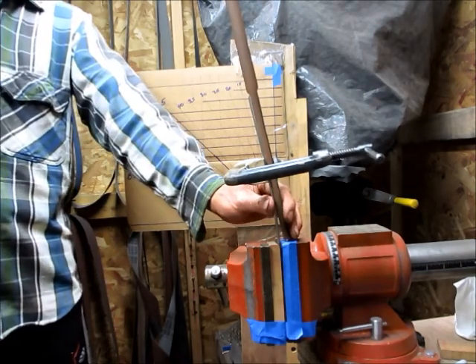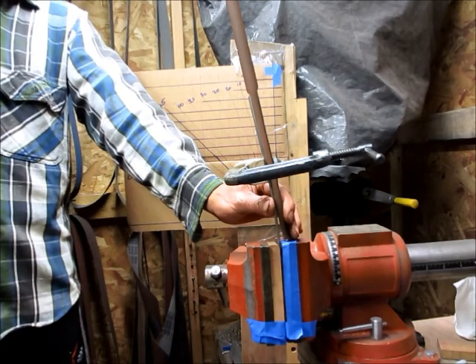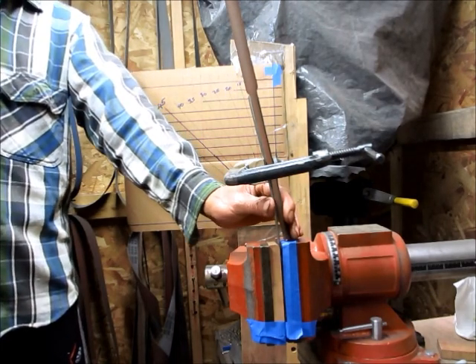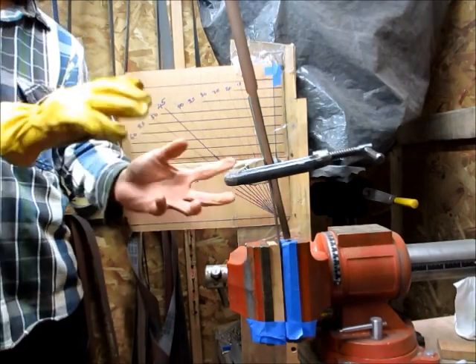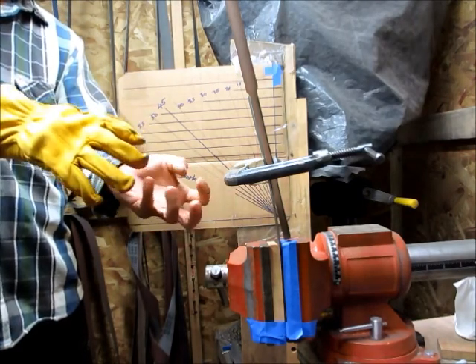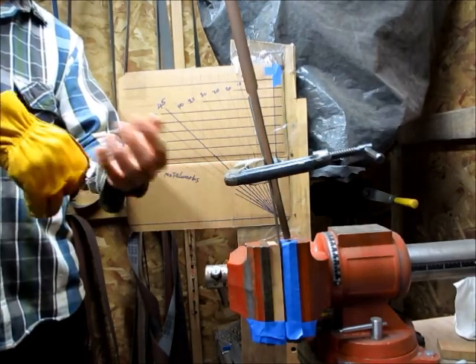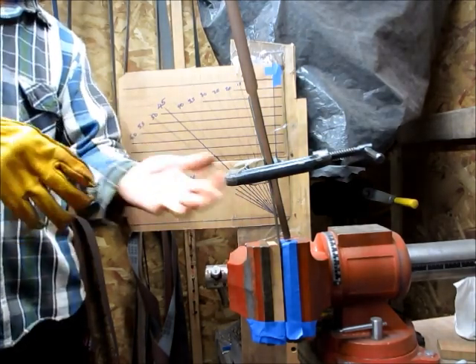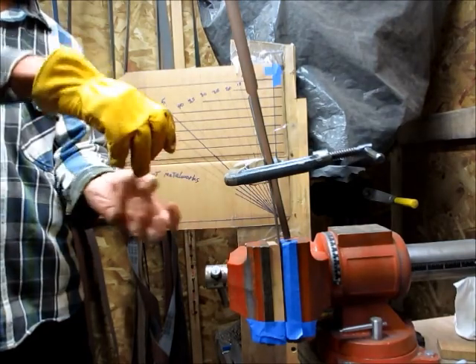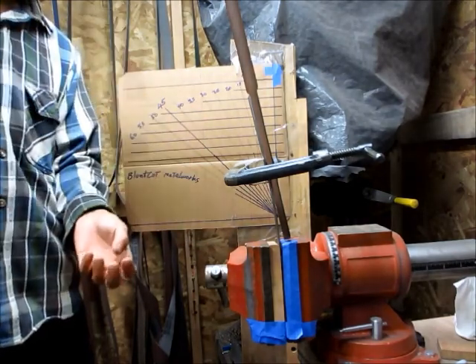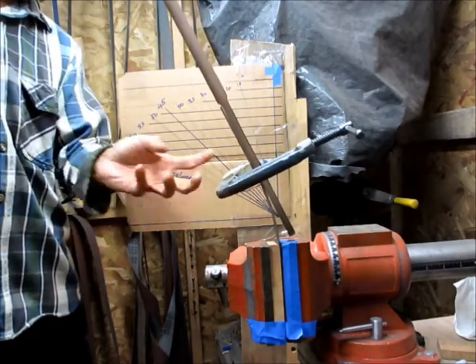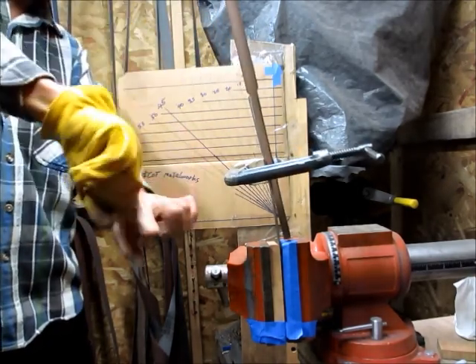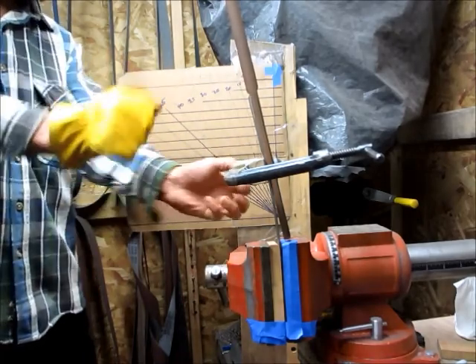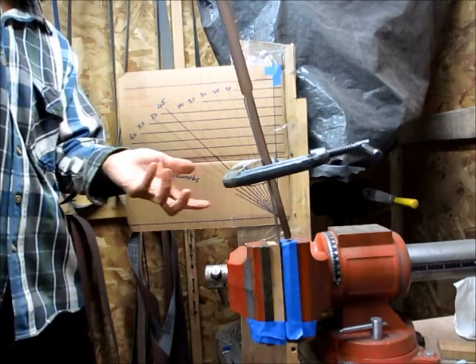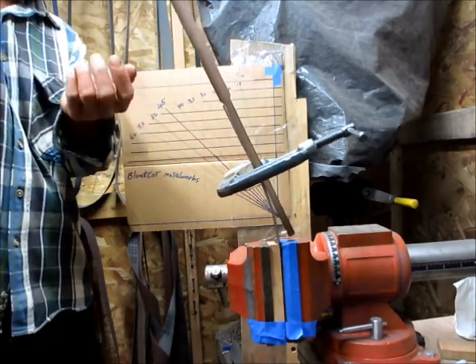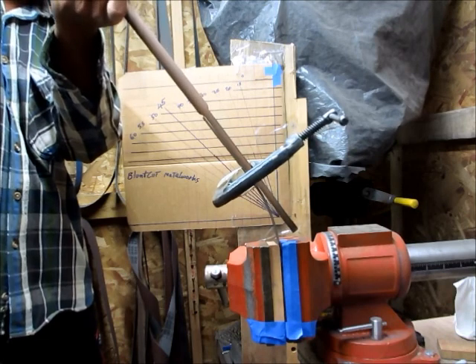The idea with grain size is that when the grains are really fine, they can rotate and move, and the dislocations move, as long as the grain boundary is not the liability or the weakest point. When you have really small grains, you can think of little small marbles that can rotate. When the grains are really big and you have dislocations or sharp angles, then when they start to move, they just snap, initiate a crack, and it propagates to a break altogether.